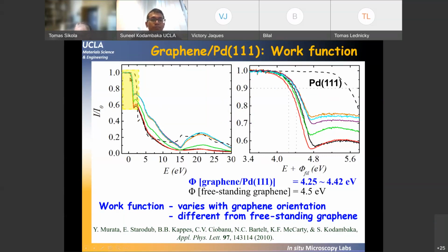Now, what I want to tell you here is that initially all the electrons get reflected from the surface, but as you start increasing the energy of the incident electrons, at some point they start interacting with the surface, and there will be a loss in the amount of intensity because the electrons start getting scattered. And the point at which they start to scatter significantly is a measure of work function. In our approach, there are slight variations, but typically in this normalized intensity, the drop in intensity to about 90%, the energy associated with that is a measure of the surface work function. And because typically one does not know the work function of the filament, you need to find that. For that, we can use the reference clean palladium, and once we use that as a reference, we can have absolute values for the work function.